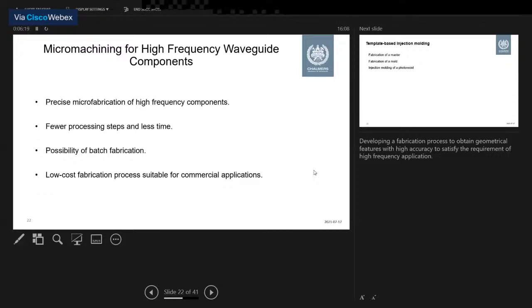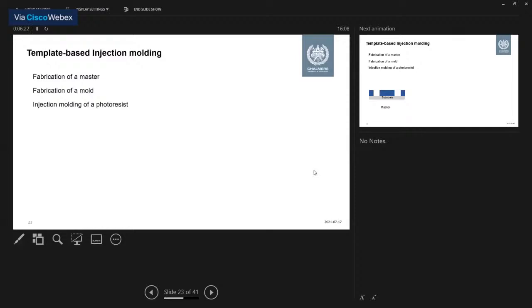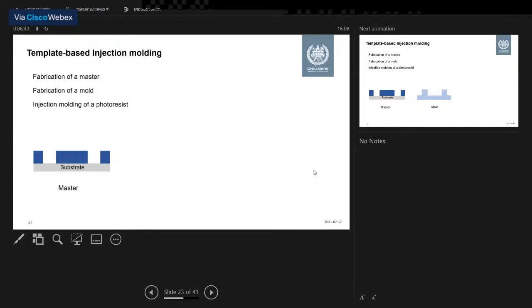So considering those issues, we developed a template based injection molding. In this template-based injection molding method, it seems very complicated at the beginning, but finally we will see how it works and solves some issues. So the first step is we fabricate a master. A master is a piece which, once it is fabricated, always stays there and we never remove it from the substrate. And usually a master contains the accurate or original geometry of the final piece.